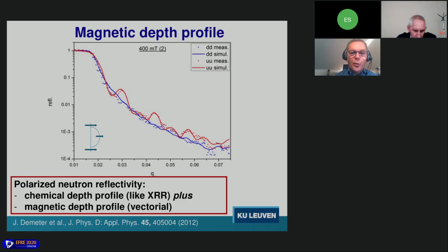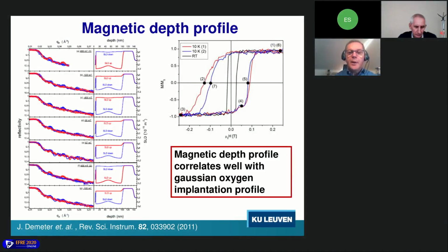I can show you that in more detail in this graph. This is our measured hysteresis loop, and we have then measured the magnetic depth profile along the hysteresis loop in these different field points that are indicated on the graph. And you see these different measurements here on the left.